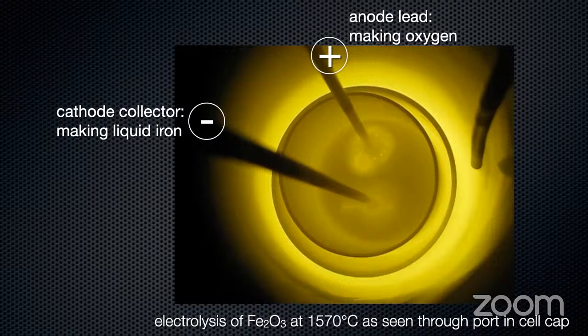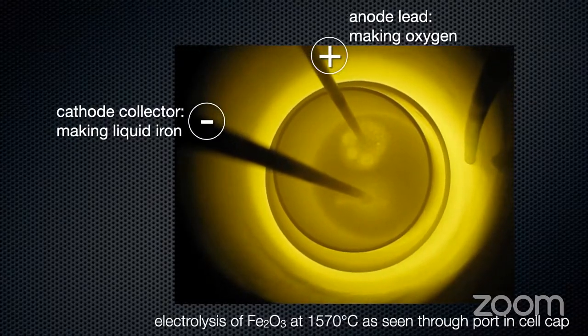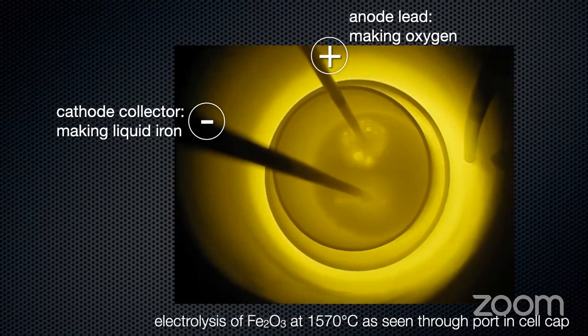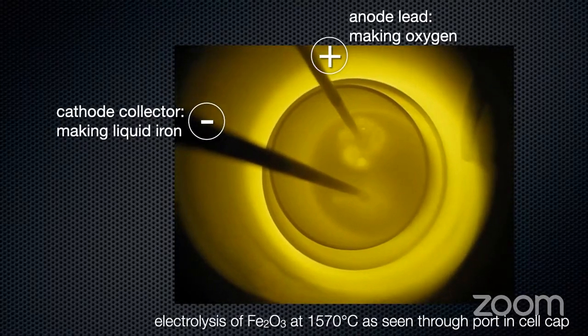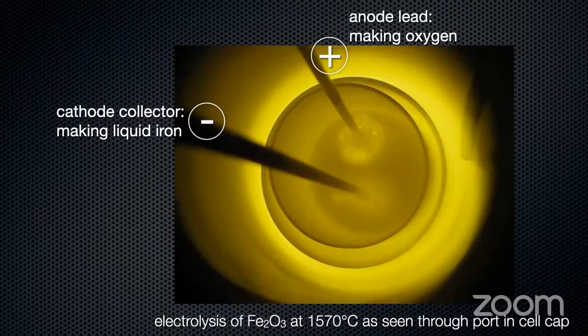And of course, we had to add external heaters because it's too small. We can't generate enough heat to compete with the radiative loss. By the way, everything that you know about how you should insulate something is wrong, because your experience is at room temperature plus or minus some hundreds of degrees. So if you want to insulate with batting and so on, the dominant, Professor Hires knows this so well, the dominant form of heat transfer at 1600 degrees is radiation. You know how you insulate? Put a thin piece of metal and you reflect it back.